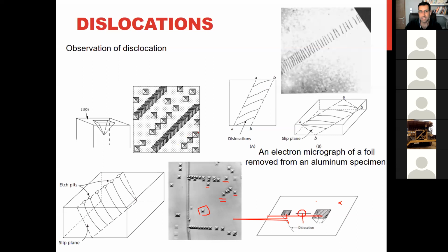And why is it like a cube or a square? Because this plane is 100, and when this is 100, the corrosion by acid happens like this, because this plane, and this plane, and this plane are 111. And these 111 planes, as they are close packed, are more stable, so the acid can corrode them less. In this way, you will form a pit like this. So under the microscope, you will see it like this. Each of these pits belongs to one dislocation.